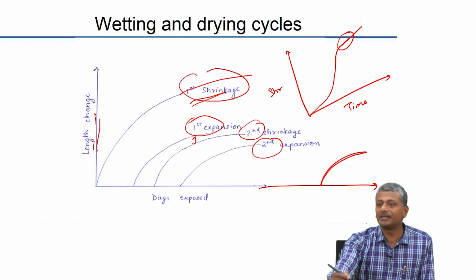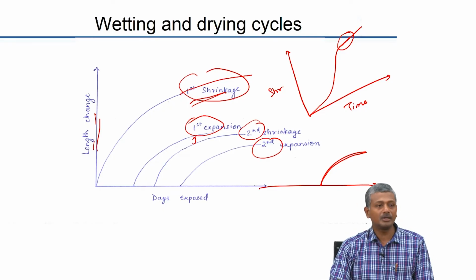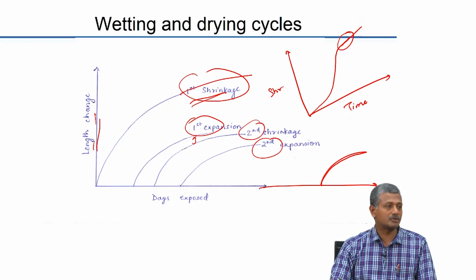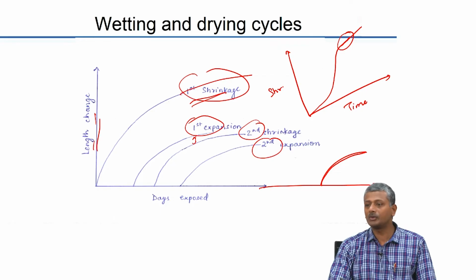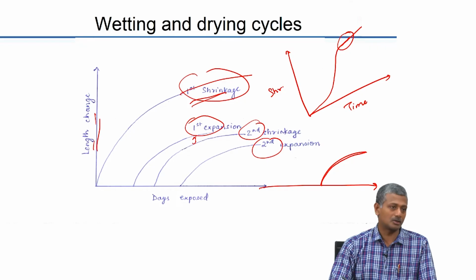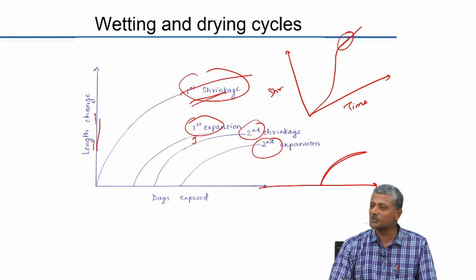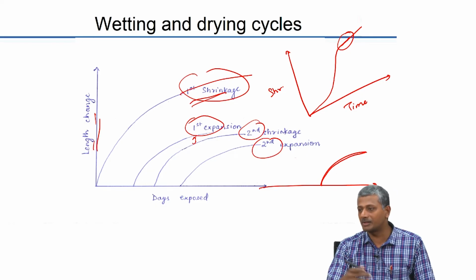If we do not do that, then the result is not really representing the true shrinkage of your specimen. Again, how much time do you need for this? 6 months to 1 year. So, when you are taking up a new mix design for a special concrete, you need 6 months to 1 year.